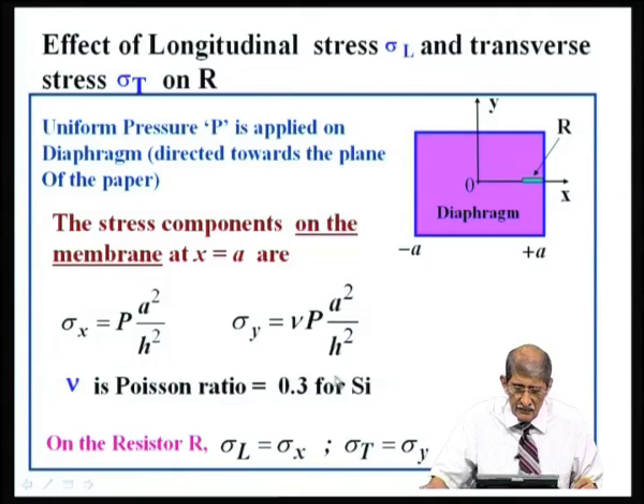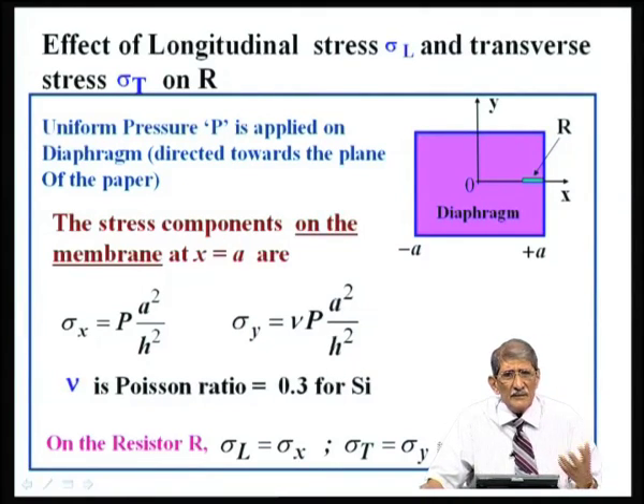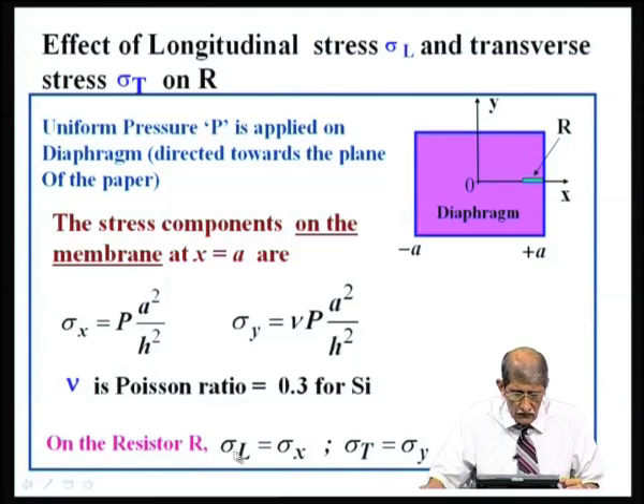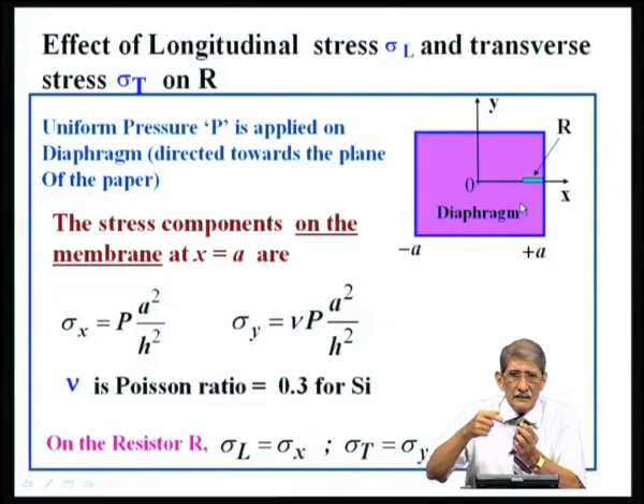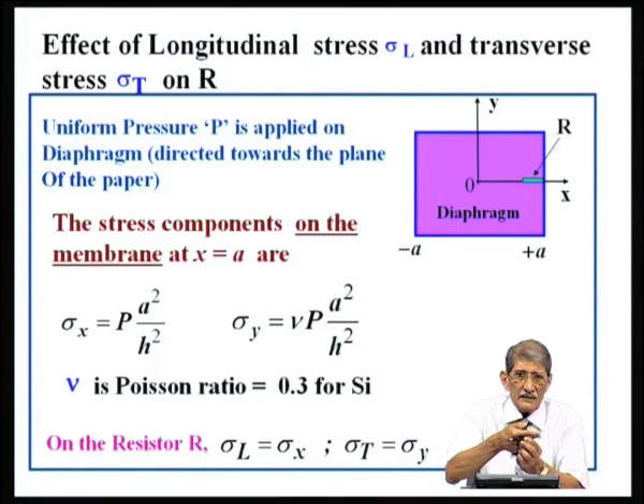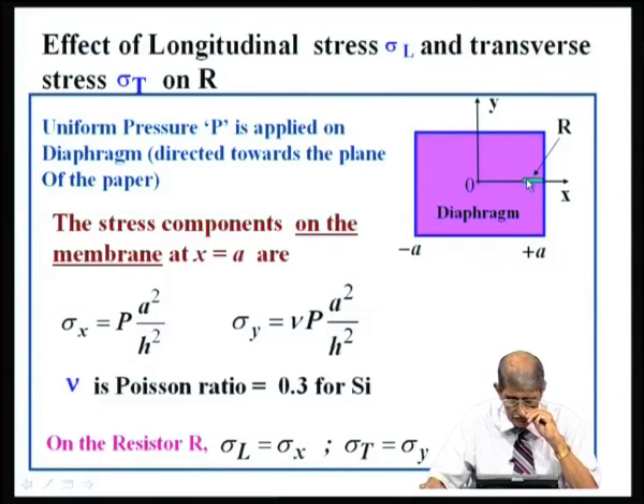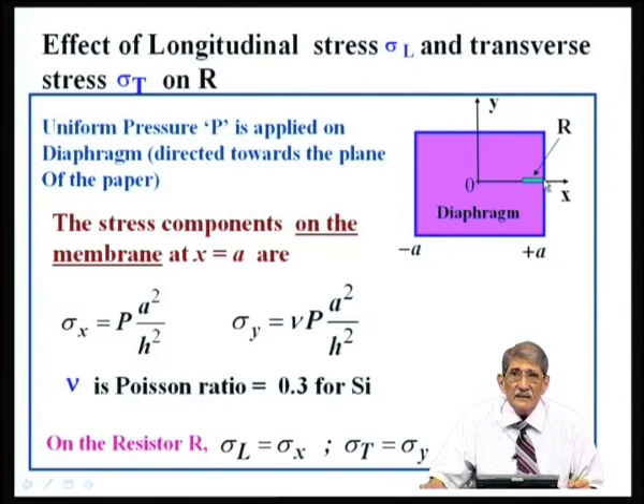Okay. For silicon it is about 0.3. It will depend upon the material, it will be of that order. So, on the resistance R which is mounted like this, sigma L is P into A by H whole squared. Sigma transverse is perpendicular to the direction of current flow. If I have the resistor located like this, the current will flow in that direction, and you call that direction longitudinal. Perpendicular to that, along the width of the resistor, is called transverse. So, if I have a resistor located like this, longitudinal is P into A by H whole square, transverse is nu times that.